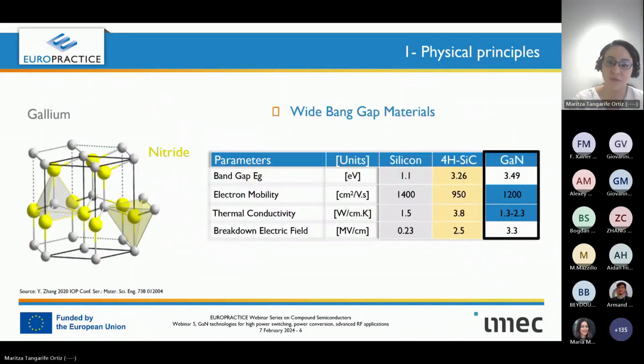So if we now compare the desired properties of GaN with silicon carbide and silicon, we can see in this table that the bandgap for GaN is 3.49 electron volts, which is higher than silicon carbide, but it is also far higher than silicon alone, which is 1.1. And we must mention here that this bandgap is direct. What do I mean? That the transition from the valence to the conduction band is immediate, that you don't have steps in the transition where you would be dissipating energy. So the more straightforward the bandgap, the fewer losses associated with intermediate states.